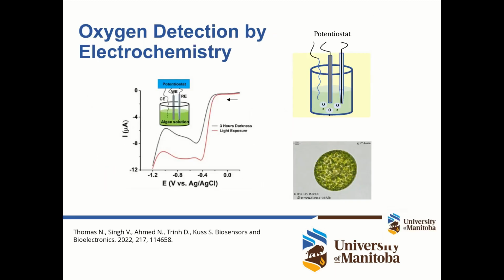Okay, so now our biological sample here are algae cells. We first had to prove that they are indeed light sensitive. So we exposed them here for 3 hours to light or 3 hours in darkness. And when we carry out voltammetry in a beaker containing these cells, we can appreciate that these cells under light condition generate oxygen. Whereas in dark, we get a much more reduced current signal here.